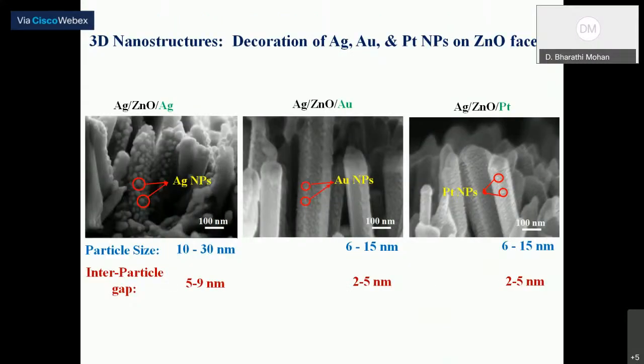So again, we have calculated the particle size and interparticle distance of the silver nanoparticles and gold and platinum decorated on zinc oxide nanorods. The particle size ranges from 10 to 30 nanometer for silver, whereas in the case of gold and platinum, it varies from 6 to 15 nanometer. Also, the interparticle gap has been calculated, and it ranges from 5 to 9 nanometer for silver, and it is 2 to 5 nanometer for gold and platinum.